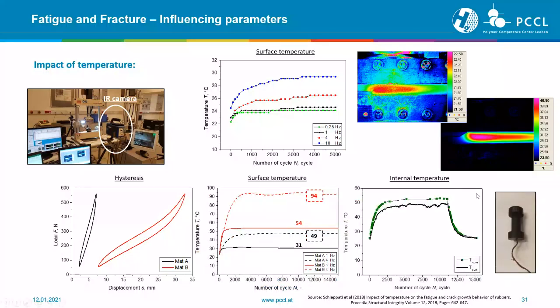Additionally, we also measured the internal temperature of such Dumbo specimens. So we directly molded the thermocouple inside of this material, and we've done this several times to get a bit of an average of what's happening. What we've seen, and also what we expected, is that the core temperature is even higher compared to the surface temperature that we measured outside of the material.